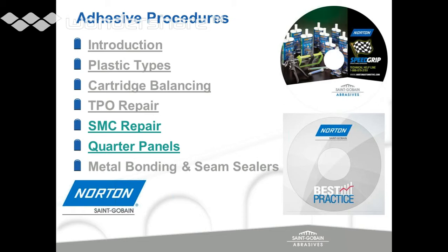Or if you've noticed, in the video, they cleaned before they did any sanding. If they happen to use a cleaner after they sanded the plastic, some cleaners, depending on what they could be, different solvents out there, might wick into the plastic and come back to haunt you and give you a bubbling effect. So we've made some changes to the line since then, but the repair itself is essentially the same. We sand it with 36 to 80 grit for a good scratch, blow it off with clean, dry air, don't add any other chemical other than the adhesion promoter so that the glue adheres to the plastic, and follow your procedure normally.